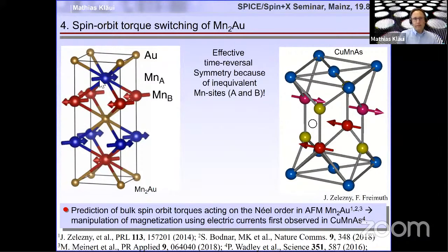And you can see this nicely. If you look at this manganese atom of the A sublattice here, it sees above gold and below it sees four manganese B sites. This manganese B site above sees four manganese A sites and below gold. And these four manganese B sites see above one manganese A site and below gold. And these four manganese A sites see above gold and below a manganese B site. So every sublattice actually knows which sublattice it is in by just looking at the environment. And so the torques acting on the two sublattices can be inequivalent because the sublattices are inequivalent.